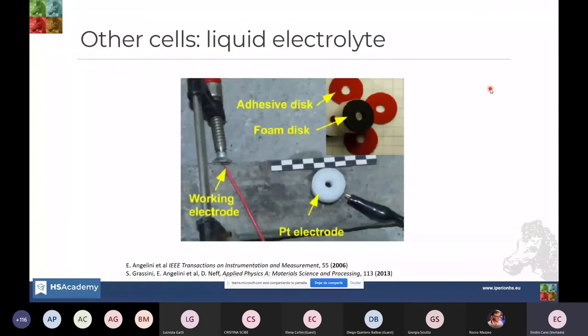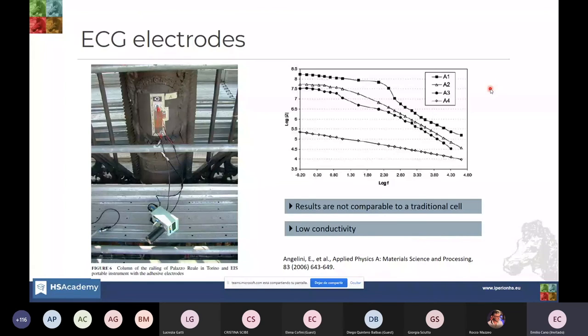But the problem of using a liquid electrolyte with this or any other system is that the electrolyte can leak. These kinds of adhesive systems cannot adhere very well to rough or irregular surfaces. In the end, it is very difficult to keep the electrolyte without leakage. Of course, you cannot measure upside down. It is a bit tricky. So there have been some attempts to avoid the use of liquid electrolytes, and one of them was also by Angelini and co-workers.